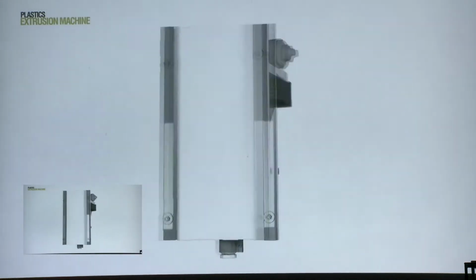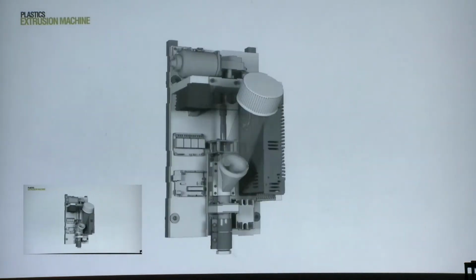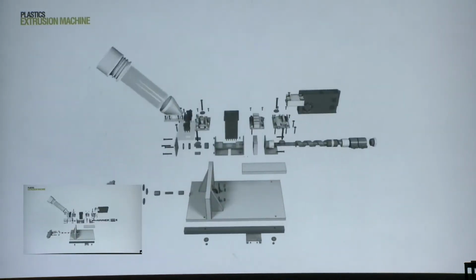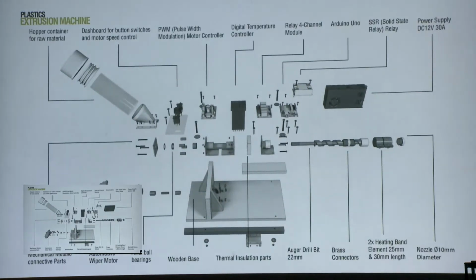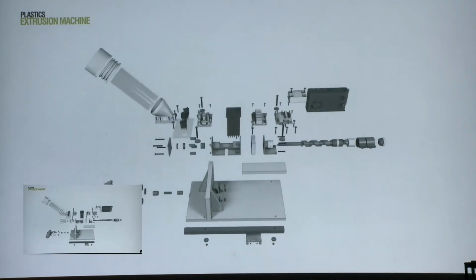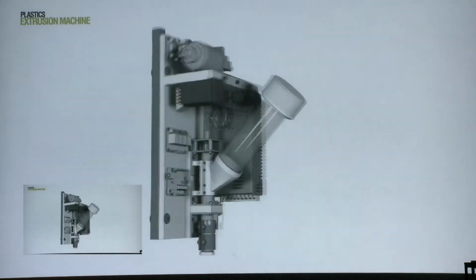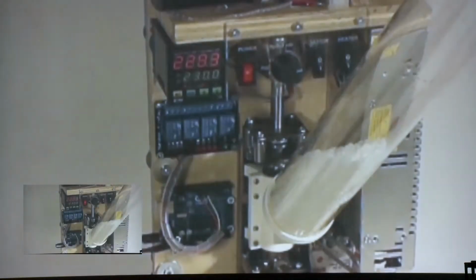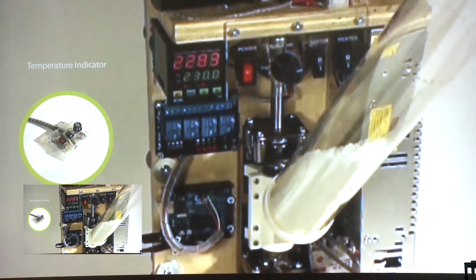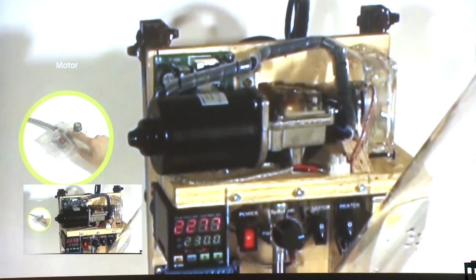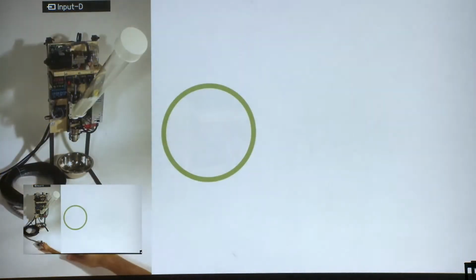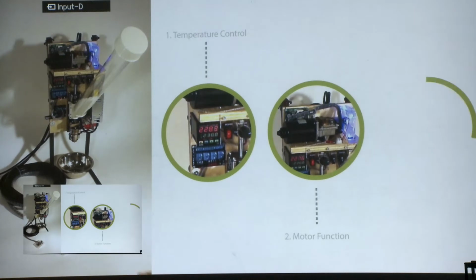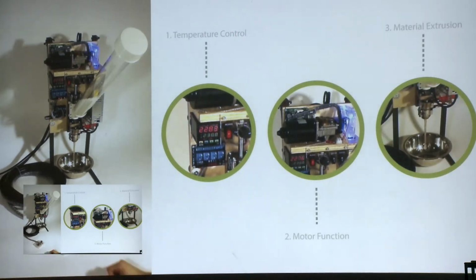As long as we have a depositing system, a deposition machine, it needs to be developed. This is an extrusion machine that takes the material as granules and extrudes it at 230 degrees as a viscous mass. It is used with a temperature controller, and we use an Arduino and a DC motor to control the deposition and the speed, in order to have an automated fabrication system.